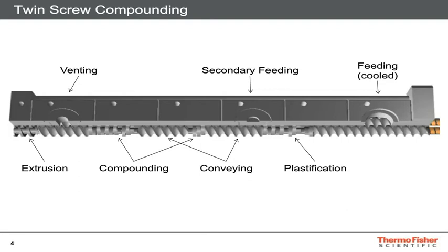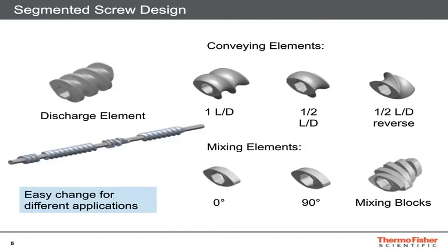So this twin screw compounder is a very, very good mixer. This mixing is so versatile and so flexible because we have a segmented screw design as shown here. On a hexagonal shaft, we are able to move conveying and mixing elements in consecutive order and really build up a screw with mixing and conveying sections as our polymer requires. With the different angles of the mixing blocks, we can also control the amount of mixing energy that goes into the process, and we can really prevent degradation of any material that is heat or shear sensitive inside that process.